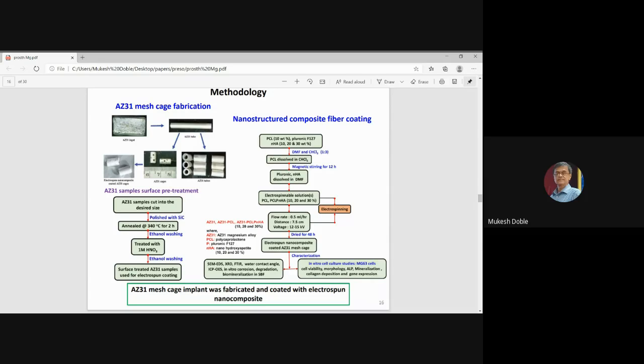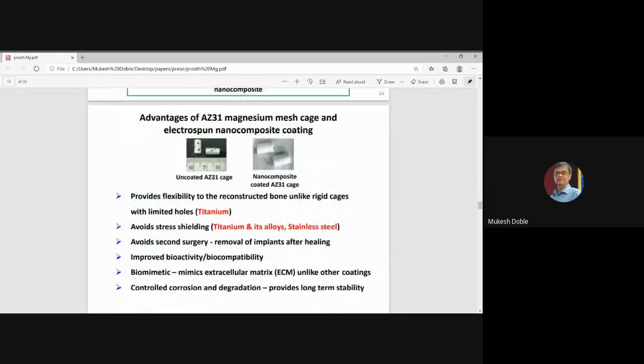So the polycaprolactone, hydroxyapatite and Pluronic acid were first coated on the magnesium cages, and then again they were electrospun on the magnesium cages. So what will be the advantage of this? You can see the uncoated AZ31 cage, and the other one is a nanocomposite coated AZ31 with electrospun polycaprolactone, hydroxyapatite and Pluronic. So it provides flexibility to the reconstructed bone.